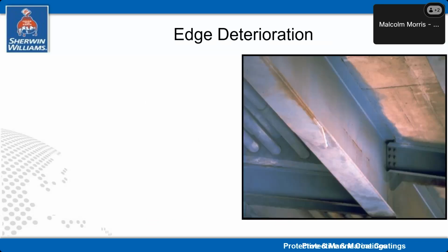So in this situation, one of the most common defects you see there is the edge deterioration. You can see on the toe of that flange, rust staining and rust spreading from there. Flange edges are a very often underestimated area of the paint job, because paint does not stick well to sharp edges. And so quite often the paint spec will specify that a supplementary stripe coat should be applied onto edges, because quite often even if the thickness is okay on the main areas of that particular section, on the actual sharp edges and corners, the paint will draw back from the edges because of surface tension, and you get a low spot on the edge, and very, very often paint will start to deteriorate from that sharp edge.